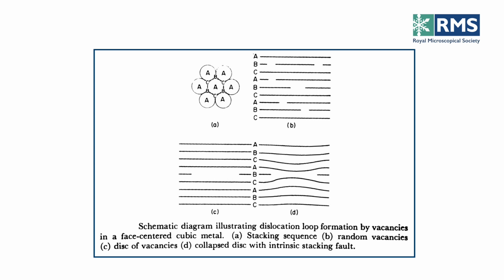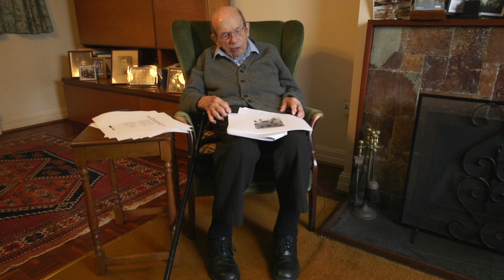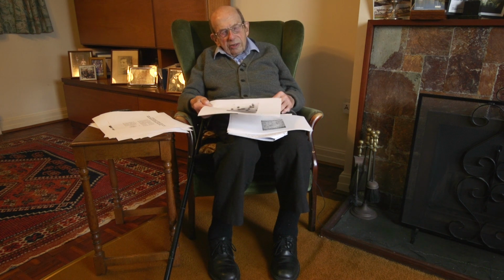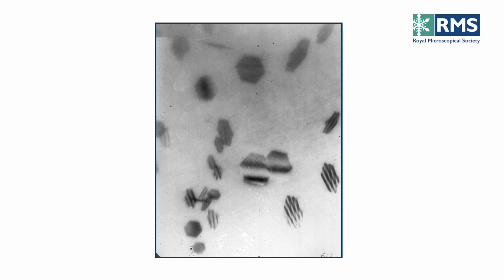loop. And for face-centered cubic materials, there are two ways in which the collapse can take place, because the stacking of these 111 planes, which are shown on this picture, is ABC, ABC. If they collapse straight down, then you get a stacking fault, because in the middle of this, A now is above C rather than above B, and that is a stacking fault, and this next slide shows you a picture of the stacking fault contrast you get from these collapsed loops after quenching.